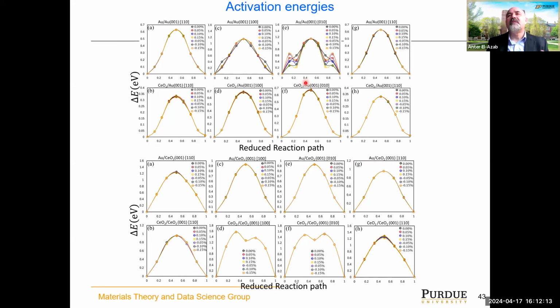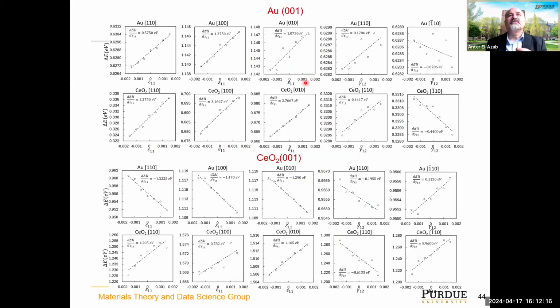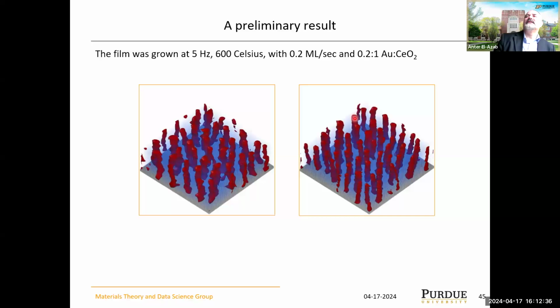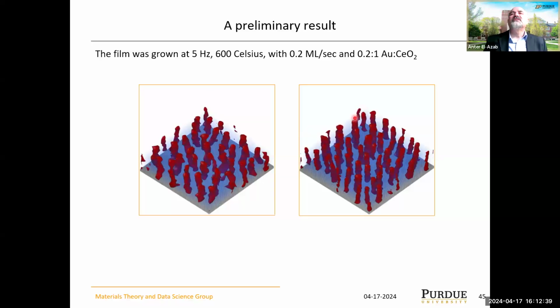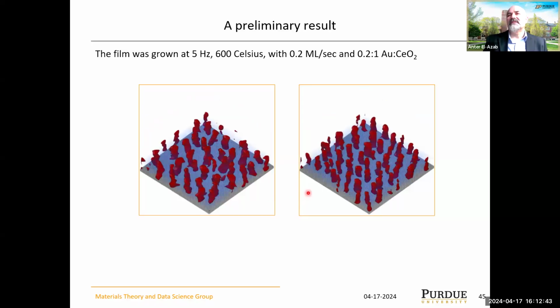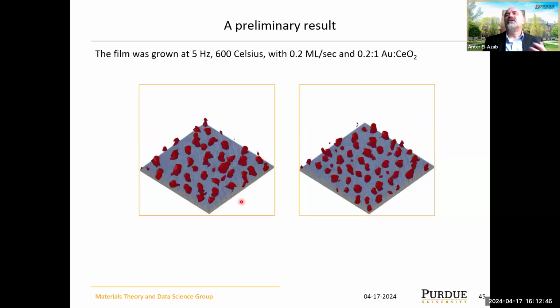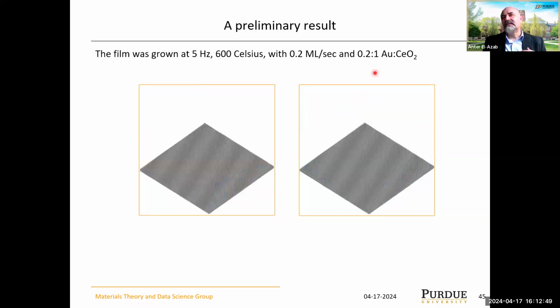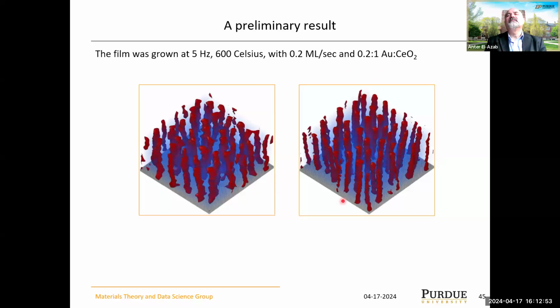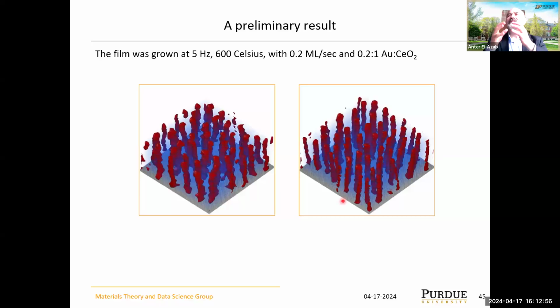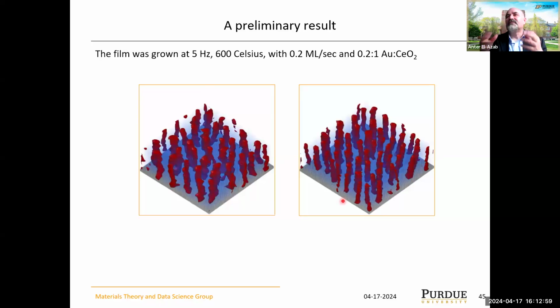He repeated the same thing for the hopping energies and cataloged, again, the dependence of these energies on the strain for both normal strain and shear strains, both positive and negative, tensile and compressive, and positive and negative shear, here for the diffusing species on different surfaces and so on. And we got all of this. He's currently in the process of putting this in the kinetics. What you see here is an old calculation that he has done to test strain effects on the kinetics of growth. And he was putting in a crude approximation of the strain effect on the hopping energy, the overall hopping energies.